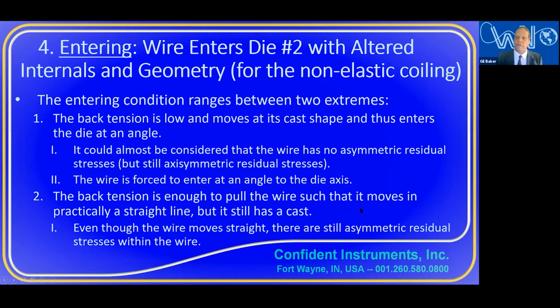Okay, so now we're entering die 2 with those altered residual stresses, asymmetric, and also slightly different geometry. The wire is not round anymore. It's slightly out of round. Now, again, this is for non-elastic coiling. If it's elastic, I forget what I said. The entering conditions range between 2 extremes. So I'm going to just show you 2 of the extremes.